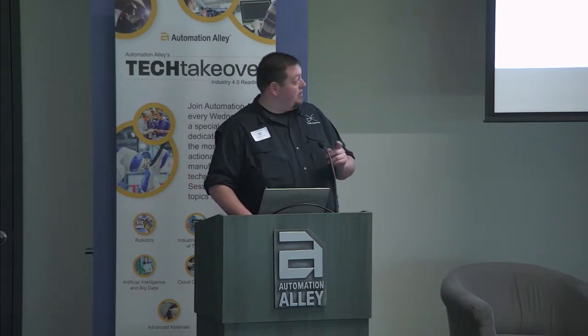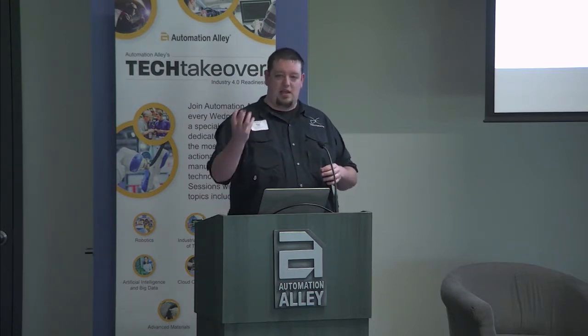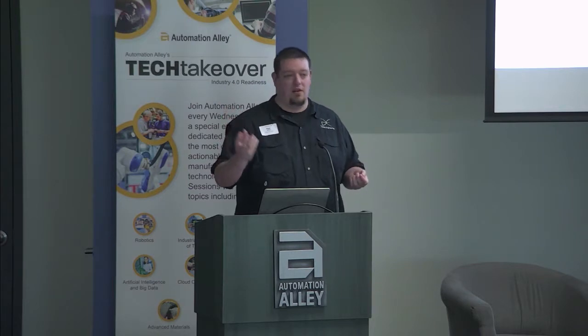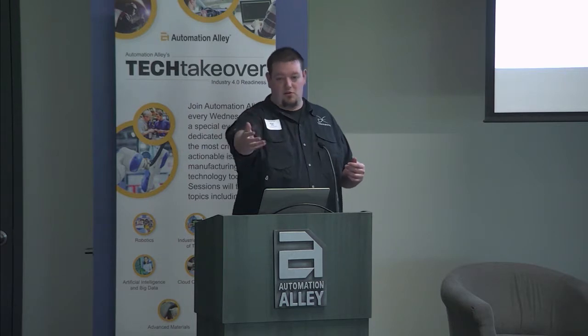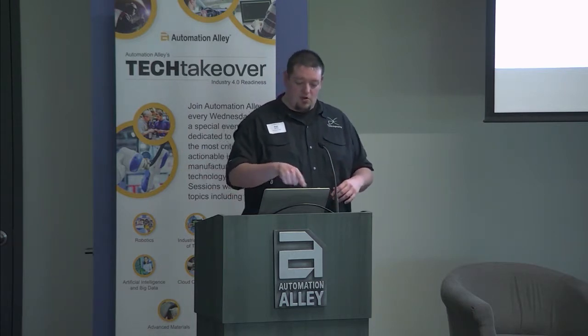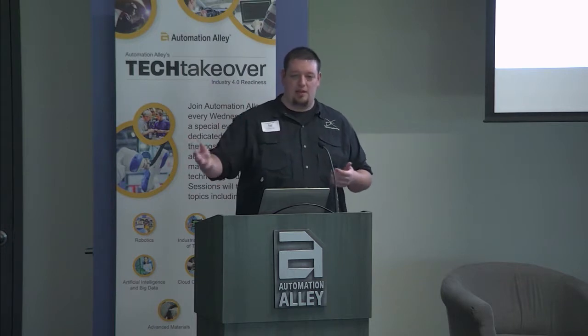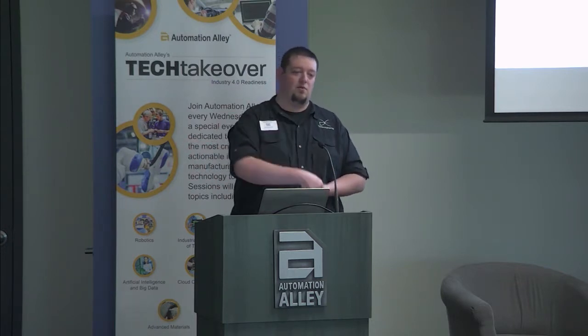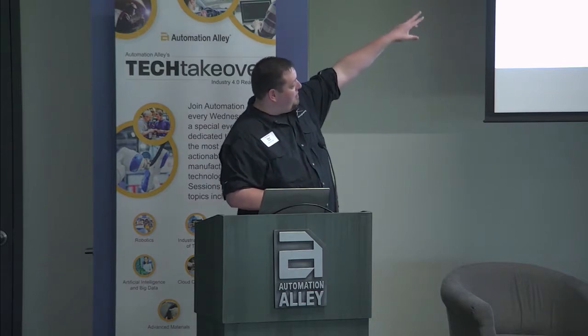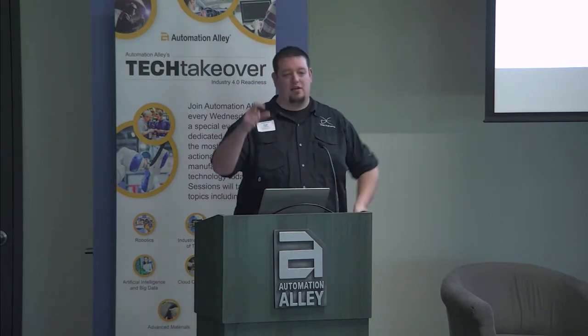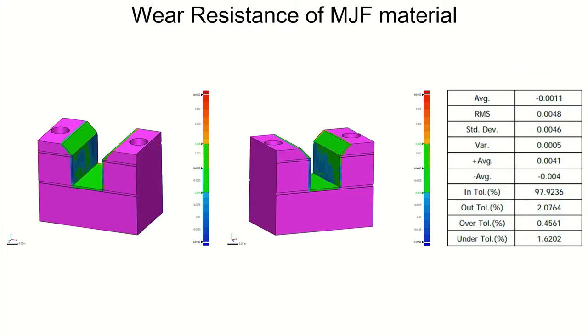Another thing that was really interesting that we wanted to check, the underside of this part is actually hollowed out. We call it a material saver. We want to cut as much excess material out of the part as we can, because whatever powder you don't sinter, you don't pay for. So we're trying to cut costs that way. So that 32 millimeter bore running at 80 psi shop air, that's about 100 pounds of force coming down and hitting full power into the bottom of this nest. Over that 100,000 cycles, we lost 2.5 thousandths to compaction. So even when you're running a cylinder into this stuff over and over and over again, it doesn't deform, it doesn't crack, it doesn't chip, it doesn't even really compact.